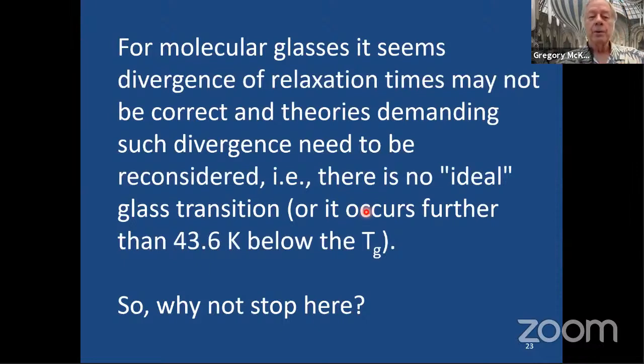So from our perspective, we thought that's pretty convincing. Molecular glasses, it seems that divergence of relaxation times may not be correct, and theories demanding such divergence need to be reconsidered, i.e. there is no ideal glass transition, or it occurs further than 43.6 degrees below the glass transition, at least in amber. Depends on the fragility, right? But so why not stop here? You know, what else could we do?